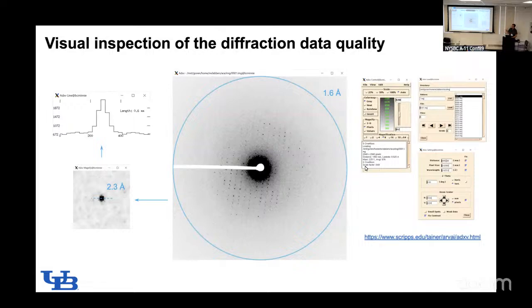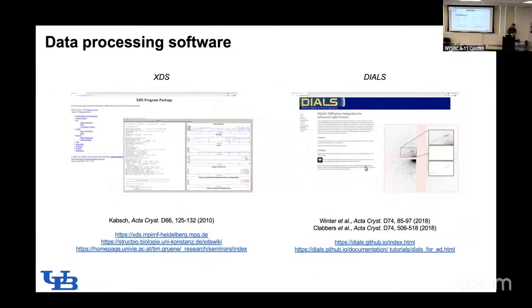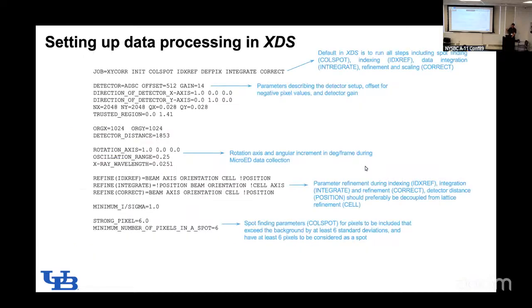So once we collect the data, I will note here that the program we use for inspecting our diffraction patterns is ADXV. All crystallographers probably have their program of choice. We also use Fiji to look at projections and things like this, or to subtract background. But ADXV is what we use to click through and make sure that it's single crystalline and we can find all spots and it's not smeary, all of these kinds of things. We processed this one in DIALS and XDS and compared them. In this case, DIALS did better, which was great.